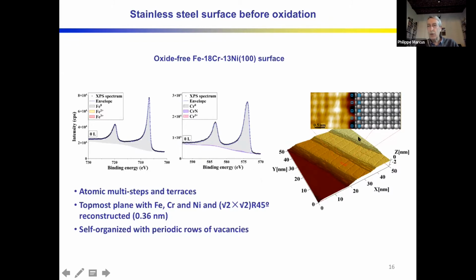And we can look at the surface by STM, and we see this interesting structure with terraces and steps. And we see that under equilibrium, there are vacancies at the metal surface. This is a completely new finding because people thought that if you had a clean stainless steel surface, you would have no vacancies. But this is not the case.